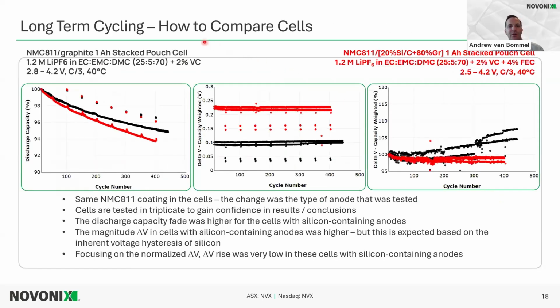So here's how to compare different cells using long-term cycling. These are some typical methods we use to compare cells. We have two cells here. In black is NMC 811 and synthetic graphite only in the anode. In red is the same NMC 811 coating. This was coated the same day, so it's just punching from the same coating. The only change here is the anode.